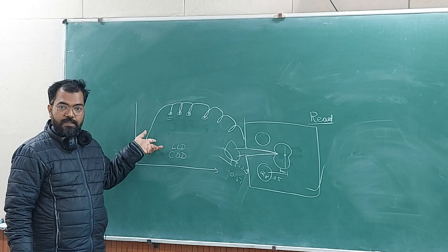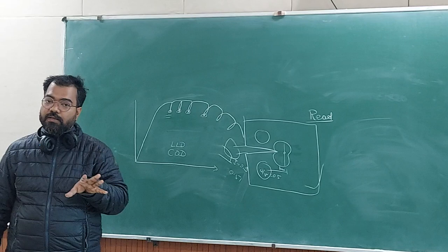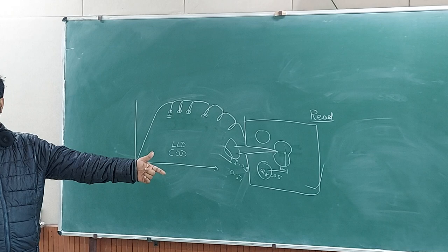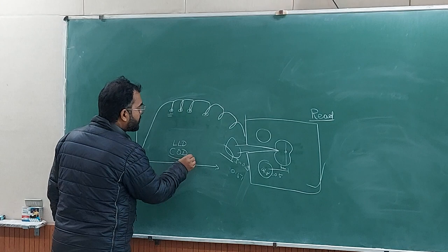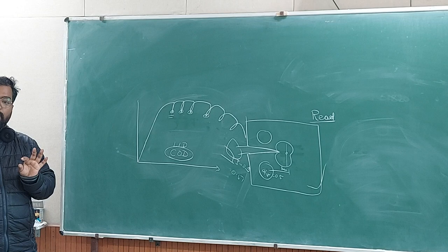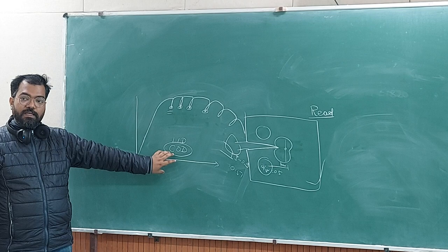So if you are taking load line displacement, then you need to have a formula which can correlate this displacement to the displacement which is happening at the crack tip. Okay, if you take COD, then also you have to have some relation. And that relation is taken care of by the displacement calculation relation with COD, which is a function of a by W, and eta factor.